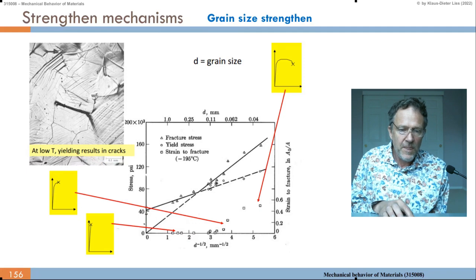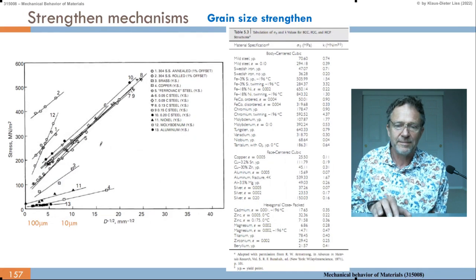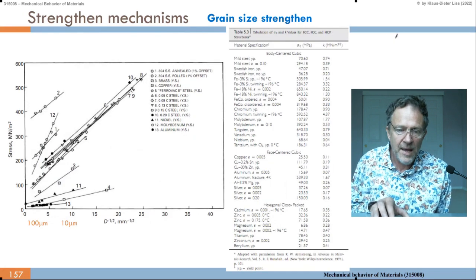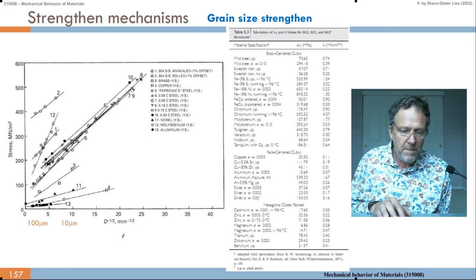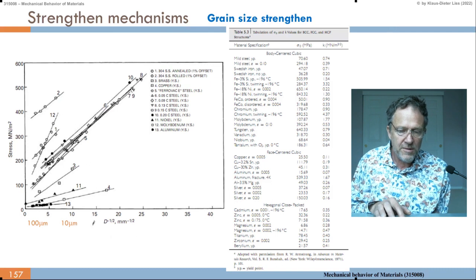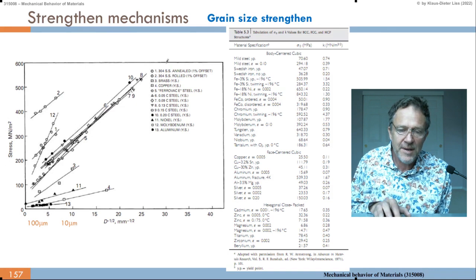So yielding, resulting in a crack at low temperature. Here more about Hall-Petch. So we have the 1 over the square root of diameter here and the applied critical stress. And we see for many materials they behave very well to the Hall-Petch law, Hall-Petch equation. So we get these linear fits to the data points.